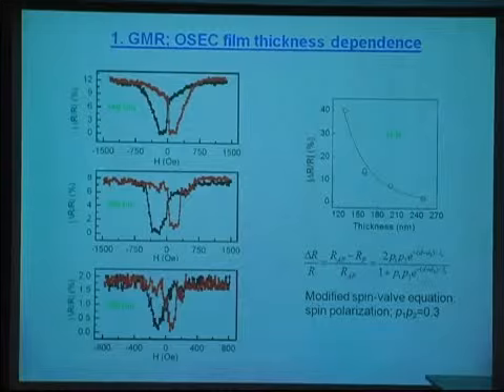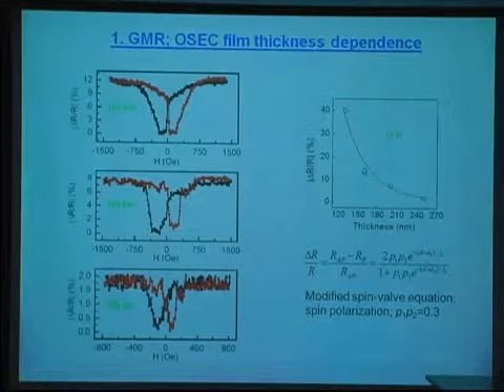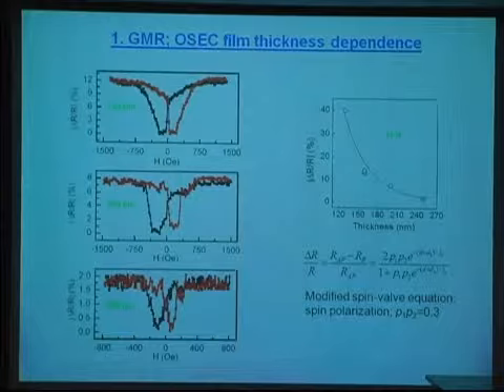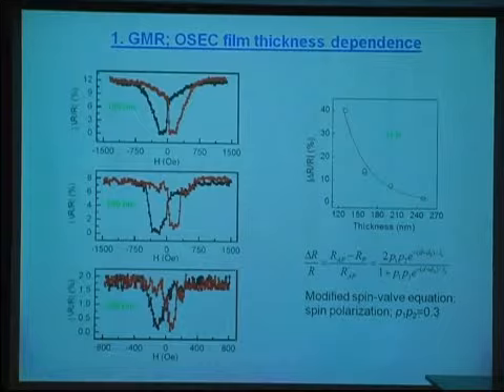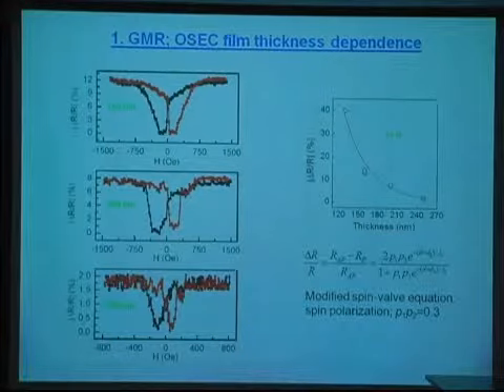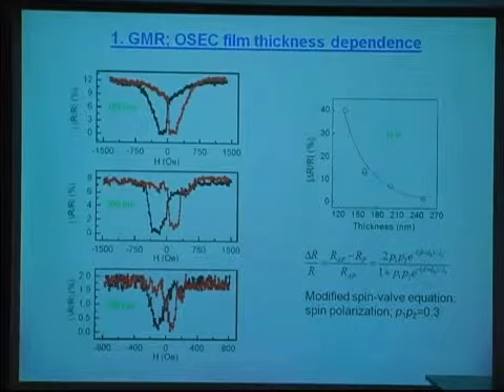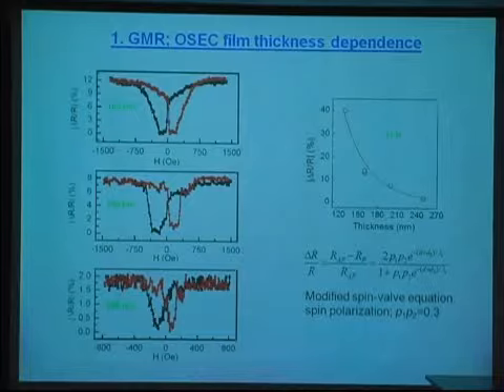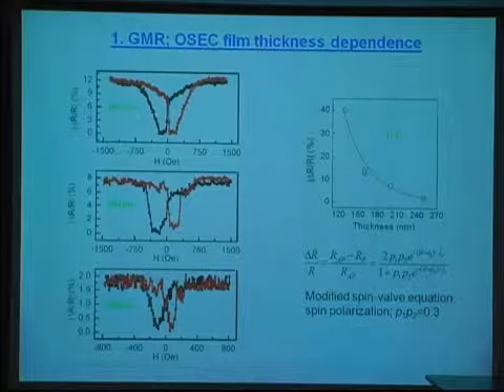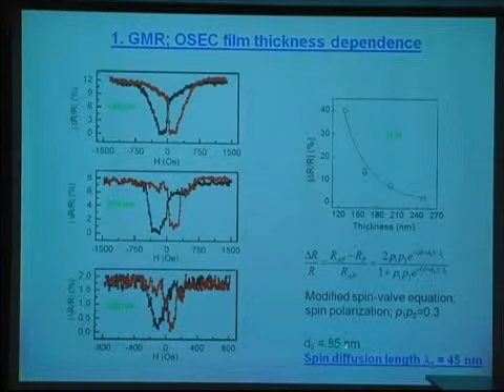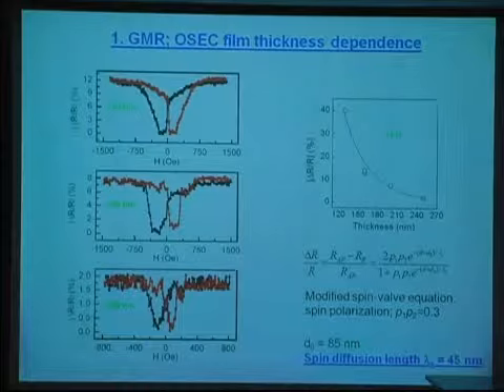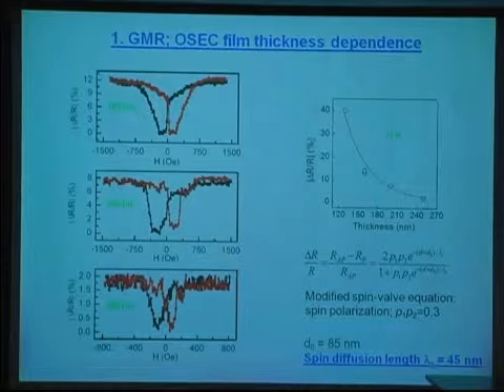Okay, let me tell you about what happens for the Alq3. Alq3 is a very soft material. When you thermally evaporate the cobalt electrodes on top of the Alq3, the hot cobalt particles penetrate into the Alq3 to a certain depth, and that depth is D naught. They don't know exactly what it is, but we can get this ill-defined layer thickness by fitting. The fitting tells us that the ill-defined layer is about 85 nanometers, which is very large, and the spin diffusion length of the Alq3 material is 45 nanometers.